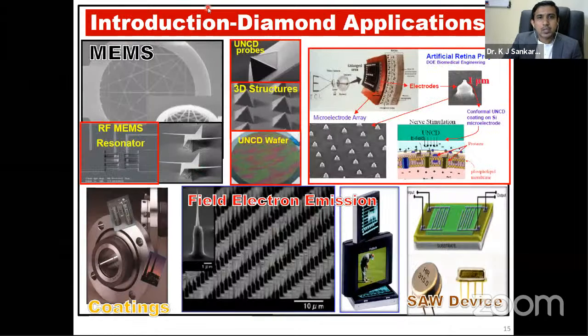We can use diamond materials for various applications, especially for micro electromechanical systems. This is for microelectronic devices that can make radio frequency resonators, and UNCD probes, where the UNCD films are coated on these tips and also on some 3D structures. This is a very uniform UNCD film on wafers that can be used for some electronic applications. And because of the very smooth surface of UNCD, it can be used for coatings. So uniform coatings can be achieved on wear bearings.